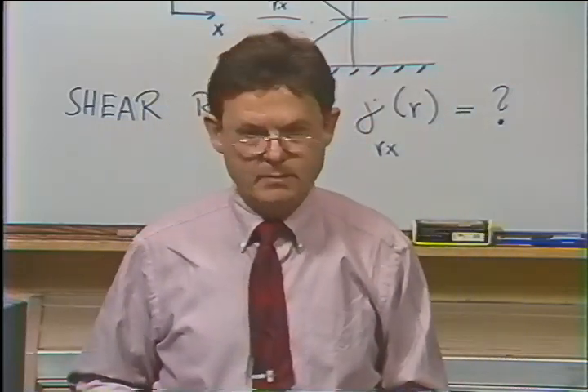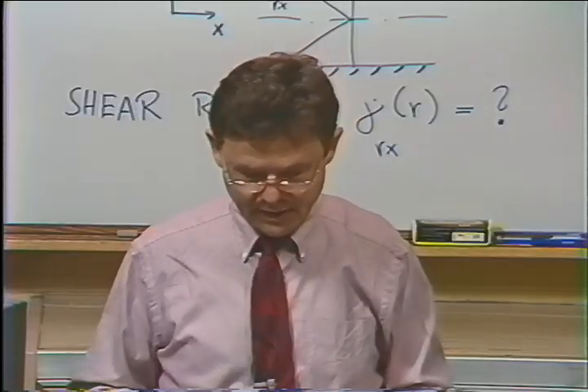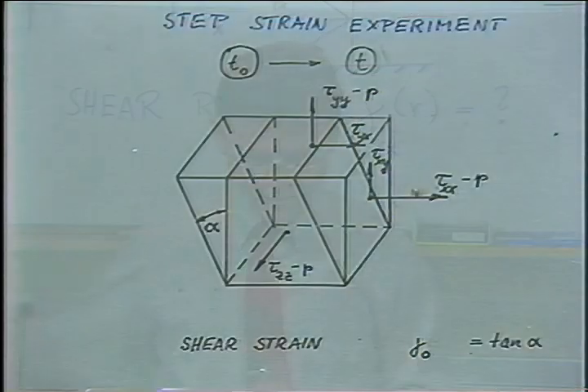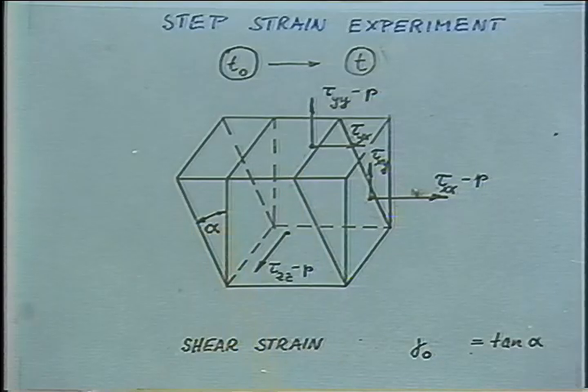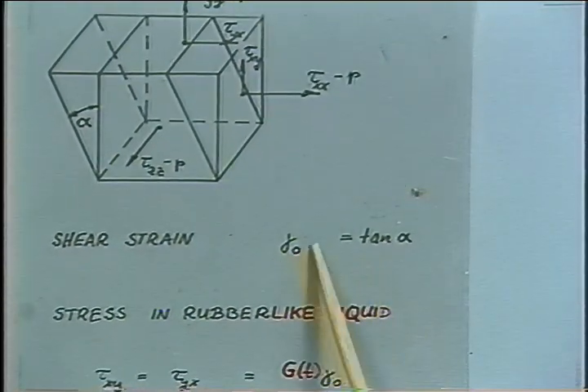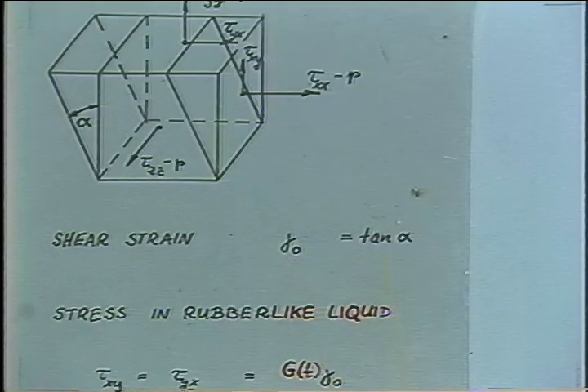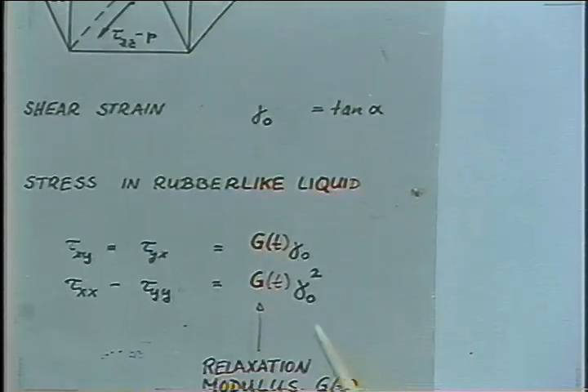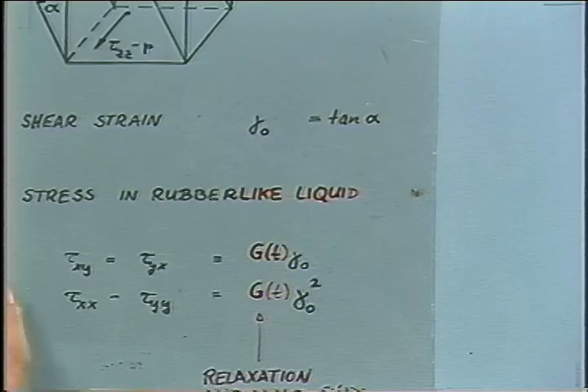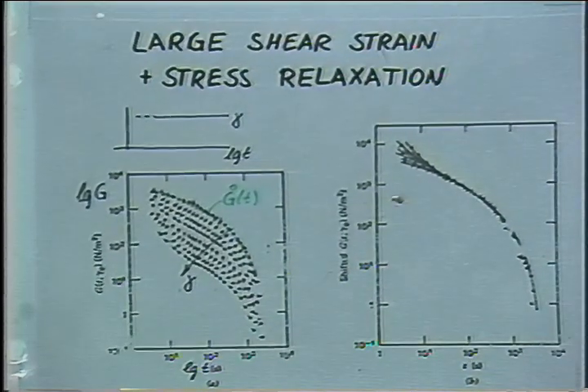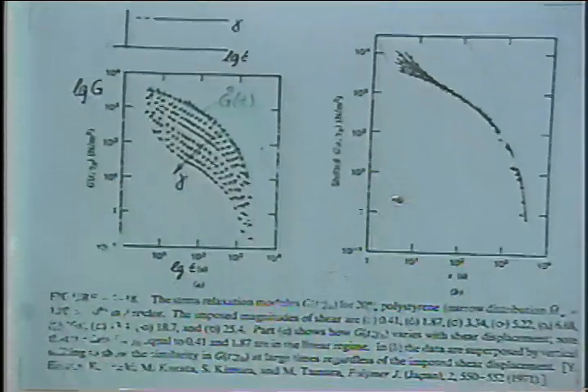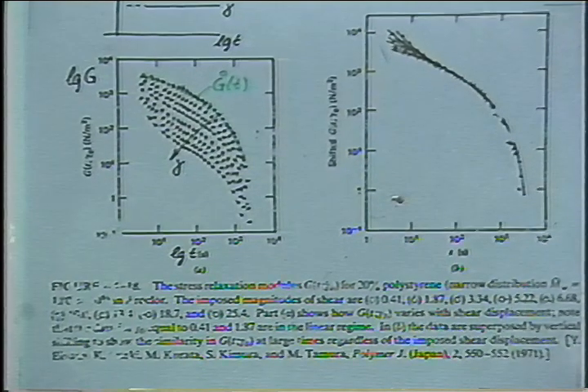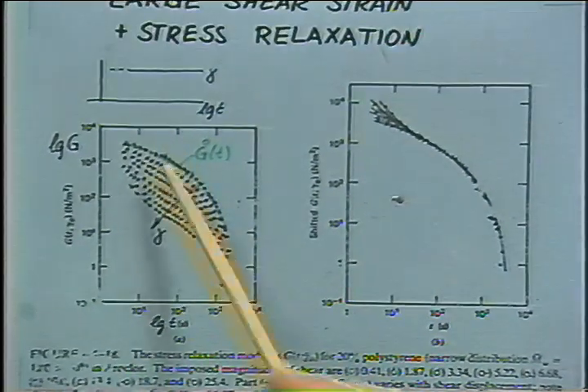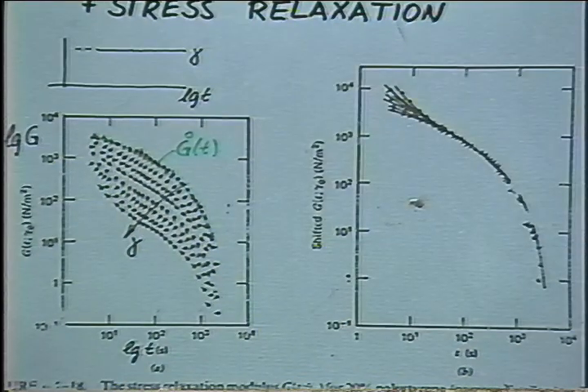Okay, now let's measure another material function. Remember, we deformed the sample in a step strain experiment, something like this. The sample was sheared by some angle alpha, and we had a strain gamma 0 imposed on this material. And we wanted to measure the relaxation modulus as a function of time. And the person who produced very, very nice data of this, even for large shear strains, was Osaki and his group. And those are the data which we discussed already in connection with material functions. You have this data.